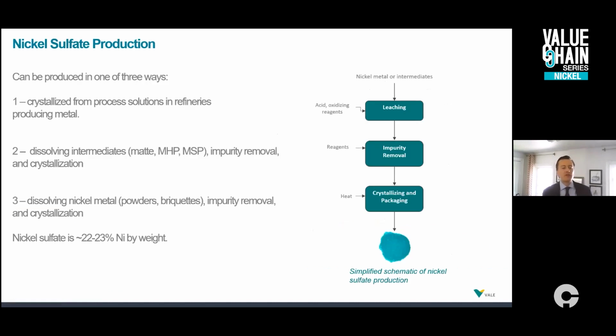Finally, nickel sulfate production really can be produced in one of three main ways. It can be crystallized from process solutions in refineries that are already producing nickel metal. So there are examples of this around the world. You can dissolve an intermediate like MHP, like MSP, with the intention of only producing nickel sulfate and not producing metallic products. That's happening maybe more frequently now than it has in the past. And finally, you can dissolve nickel metal powders or briquettes, and even other forms for that matter, and then crystallize the material as nickel sulfate.